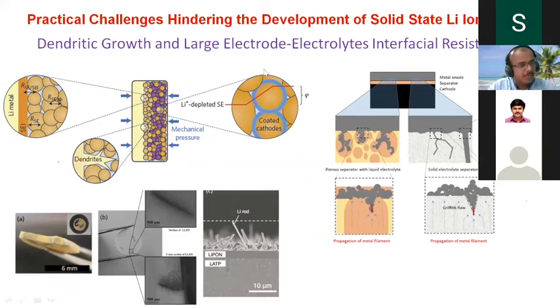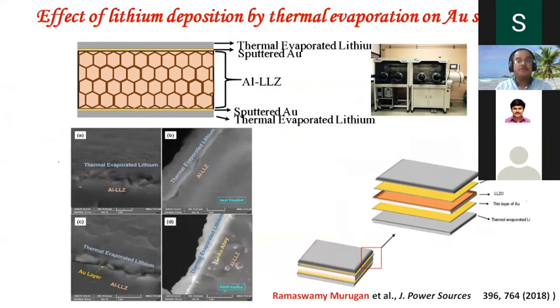What's the reason for this dendrite growth in solid lithium ion conductors? People realized it was uneven current distribution. People started to introduce buffer layers, whether metal oxides, non-metals, or polymeric layers, and with so many approaches people have been able to overcome this interfacial resistance. At the same time, they were able to overcome what we call dendritic growth.